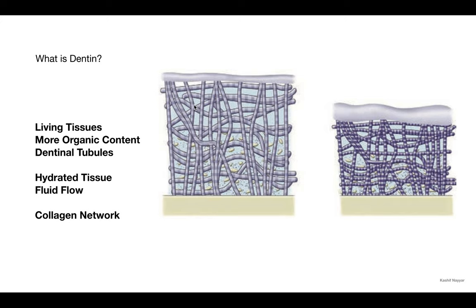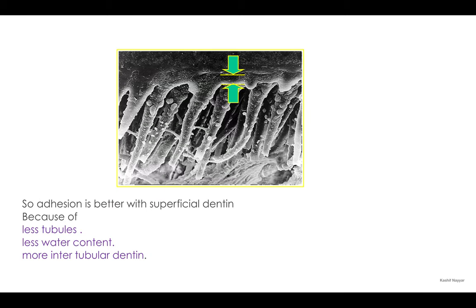And if you over dry the dentin, you are basically desiccating it and removing the excess water. And when the water is evaporated from the dentin, the upright collagen fibers just collapse, leaving very little surface area for the bonding resin to penetrate. Okay, so that's why you get less bonding strength, and it is never recommended that you desiccate your dentin. Always, always, always keep your dentin slightly moist so your bonding resin can better penetrate and give you excellent bonding strength.